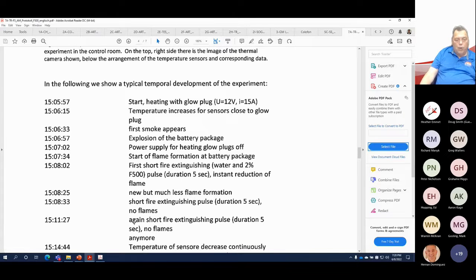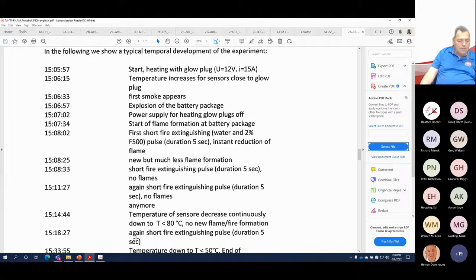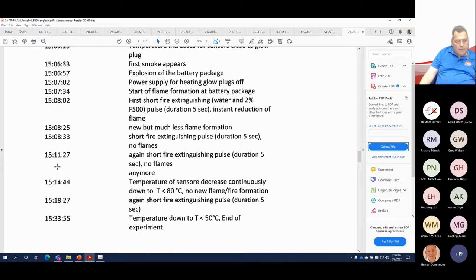So now we do a third 5-second burst. No flames are visible. And now we wait 3 minutes and we see that the temperature of the sensors has decreased continuously down to 80. There's no new flame formation. And now we're going to do another fourth 5-second burst.